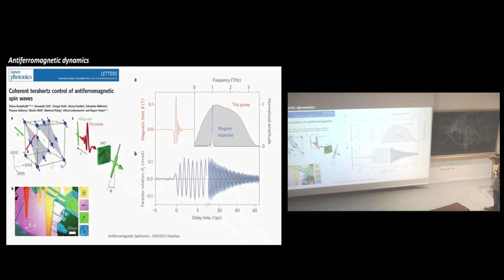And the thing you can also see here is the decay. The decay is important because that will be the damping, the way you relax to equilibrium. And we need low magnetic damping. Why? Because the higher you go in frequency, the shorter your lifetime will be. And the lifetime also depends on the damping. So you want a low damping to increase the lifetime, because if you want to do some magnetic computing, then you want magnons which live long. This is the reason we need such low damping. And this is why we're also interested in oxides, because in oxides, which are insulating, damping is very low, as is the case in this NiO.